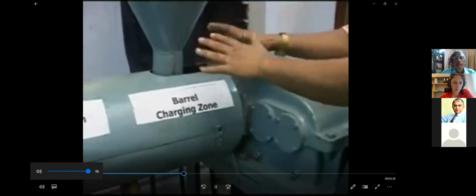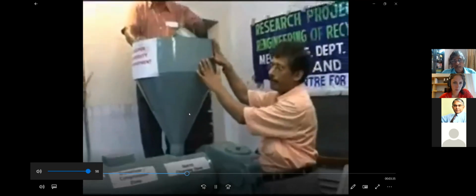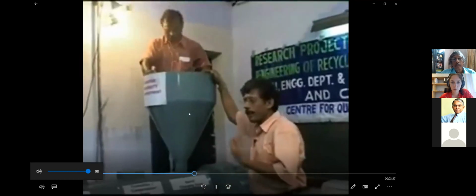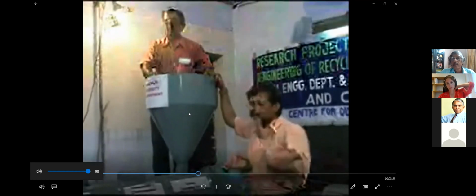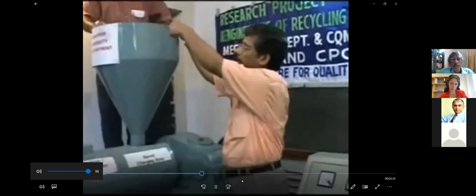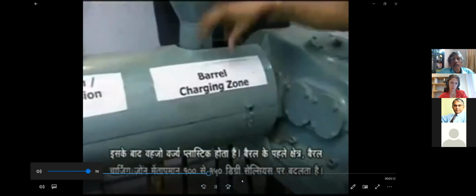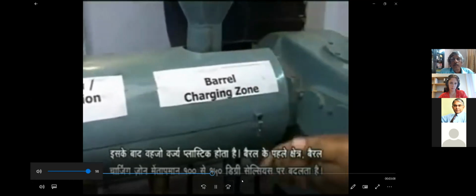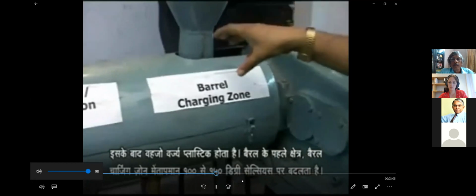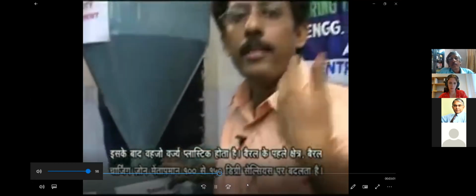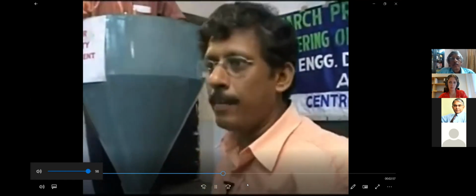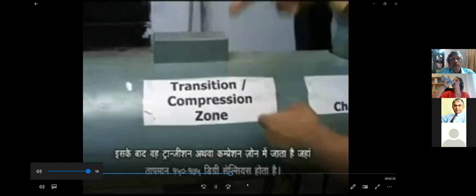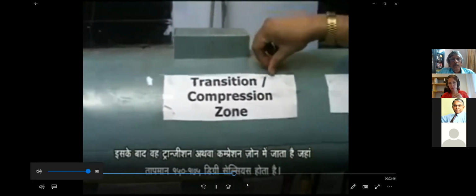So, in this barrel, the material is fed through this hopper. Now, this hopper gets the material, which is waste plastics, and we clean the material, sort the material, then we take the material from this hopper to the barrel itself. Now, you know that the first place where the charge is made is the barrel charging zone, where the temperature is around 100 to 150 degrees centigrade. I'll tell you the temperature of these different zones depends on the material itself, whether you are using LDPE, LLDPE or PP. Now, from this charging zone, the material goes to the transition or compression zone. This is the point where the temperature varies from 150 to 175 degrees centigrade.